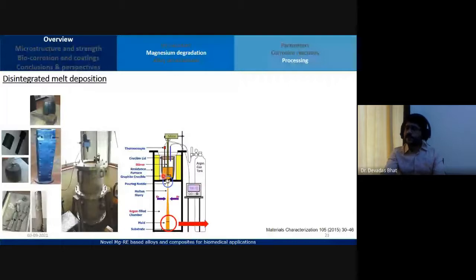So once everything gets melted, it will take about 2 hours or so. We then use a motor and stir it so that they get uniformly distributed. And then we start the argon flow here, right? And when the pouring takes place, the droplets get atomized, and then it will get deposited onto the mold. Okay. So this is how we get a billet from the DMD method.